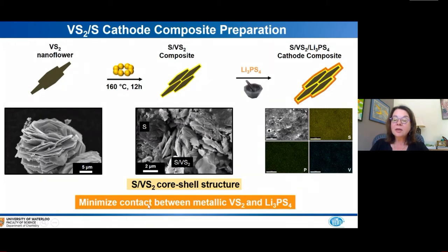This minimizes contact between the metallic VS2 and the Li3PS4, thus mitigating oxidation of the solid state electrolyte thiophosphate. And this just shows the good homogeneity of the system that we achieved.